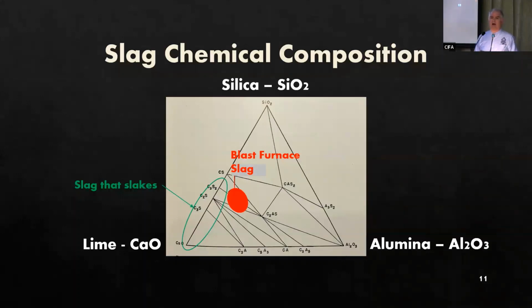I highlighted on this triangle in the orange the range of most blast furnace slags. And you can see there that the ratio between silica and alumina is about 3:1 by weight. And the amounts of silica added to alumina equals about that of lime and magnesium. Now, if the slag contained too much lime, which you see in that lower left-hand corner of the triangle, say, for example, more than 50% lime, then the slag slakes when it comes out of the furnace. It decomposes rapidly into a white powder when it's exposed to the outside elements. And that, like I said, is on the triangle down there in the lower left-hand corner.